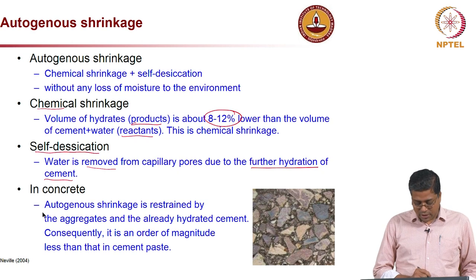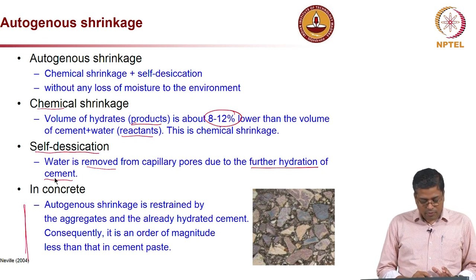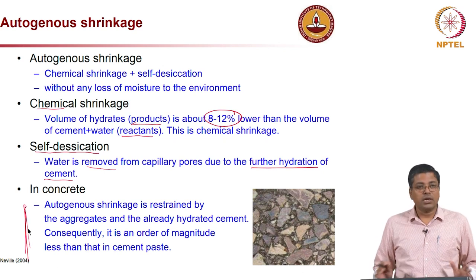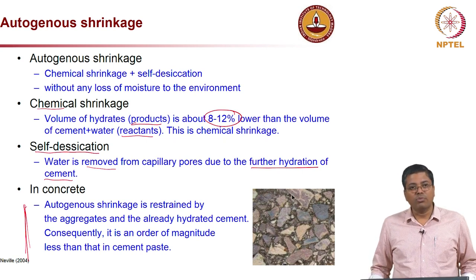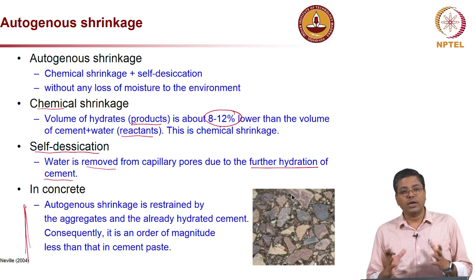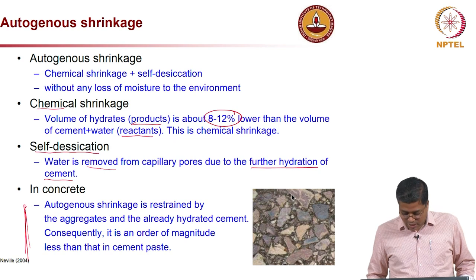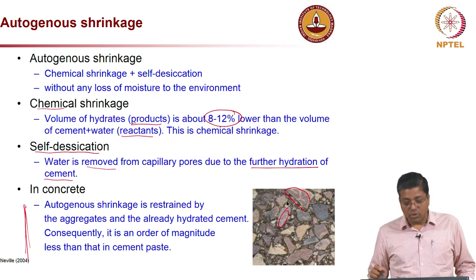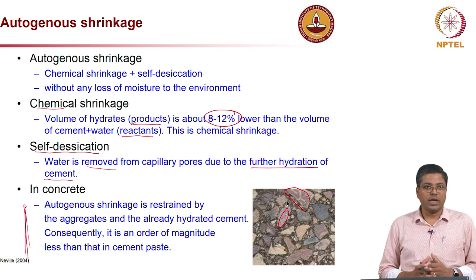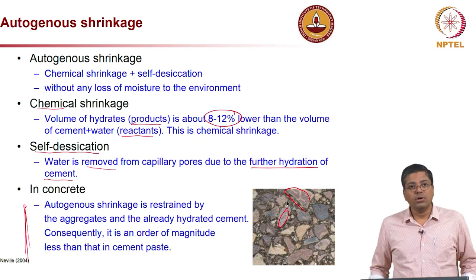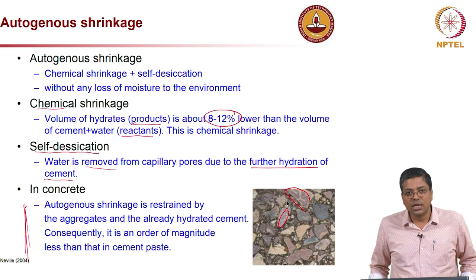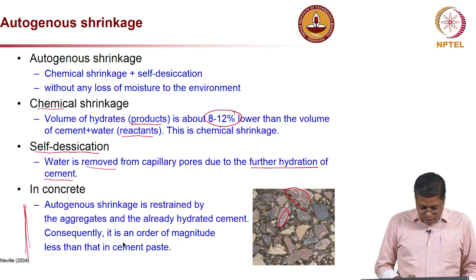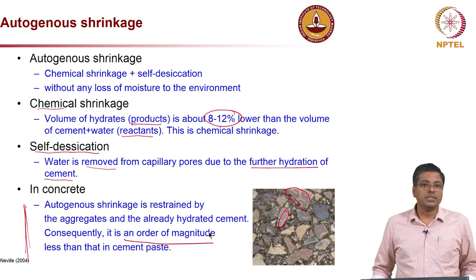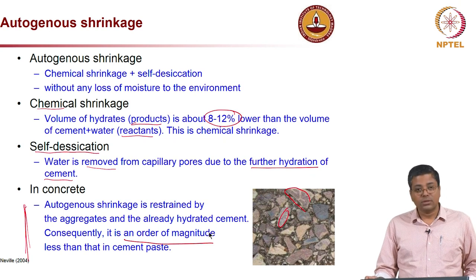Now in concrete what happens is autogenous shrinkage. When you talk about cement that is different, when you talk about concrete there is a major ingredient which is aggregate. So about 75% or even more of the concrete might have coarse aggregate, and then you also have fine aggregate present in the concrete. Now look at this picture here, you have a lot of coarse aggregates and they are actually providing restraint, and because of this restraint, the overall shrinkage might still be less. So the magnitude of shrinkage in concrete could be significantly less than that in the cement paste, one order of magnitude or 1/10 we can say.